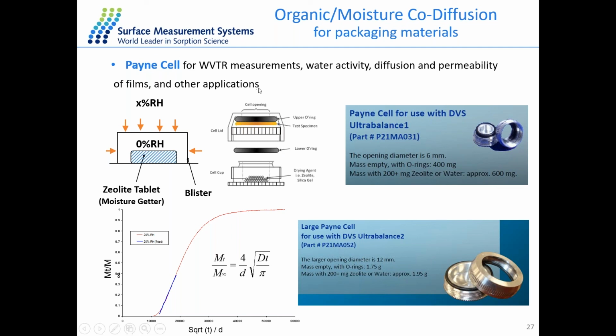So with the Payne cell, we can measure the moisture transmission rate, the water activity, as well as the diffusion or the permeability of the thin film sample. To start the experiment, we will first put some drying agent inside the cup here, and then we will seal the cup with the film of interest. And we change the outside concentration with our DVS instrument for different concentrations. So the vapor molecules will just penetrate the film from the top to the bottom in one-way direction only. So we can measure the one-way diffusion coefficient as well as the permeability of the film sample.